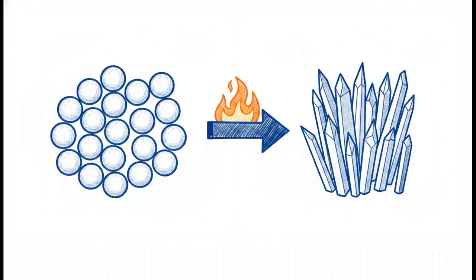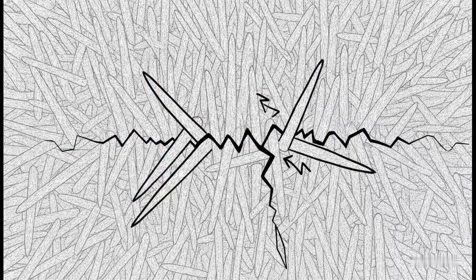Silicon nitride exists in two vital phases. First, you have the alpha phase, which dictates the initial densification. But during that high-temperature sintering process we just talked about, there's a crucial phase transformation. The material literally shifts from the alpha phase to the beta phase. And it is this beta phase that dictates the grain morphology and ultimately the final incredible toughness of your engineered component. As it makes that shift into the beta phase, it forms these unique, elongated, needle-like beta grains.